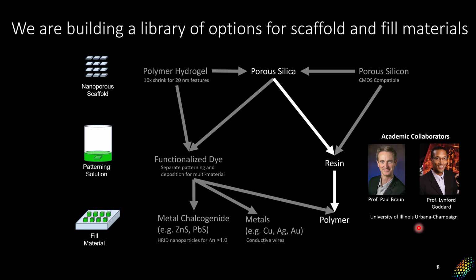And then silica and polymer are quite absorbing in the UV. And then they're nice and transparent up to the shortwave IR, but once you get into the midwave IR, the polymer starts being pretty absorbing there as well. So that's where we're looking at some of these alternative fill materials like zinc sulfide, which can be nice and transparent up to higher wave bands.